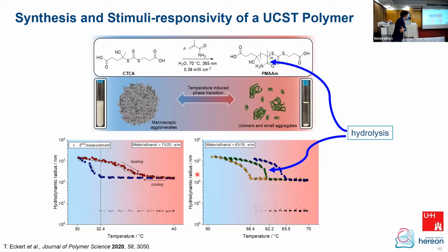And then, if you leave the system for quite some time, 3 days, then you see this effect. If you are short at a high temperature, you will not see much effect. It's a question of time, but still, 3 days at 70 degrees, you can say that's too long, but maybe you need it for certain applications. We want to have something more robust, something that can survive 70 degrees for a longer time. Yeah, if possible. Thank you.